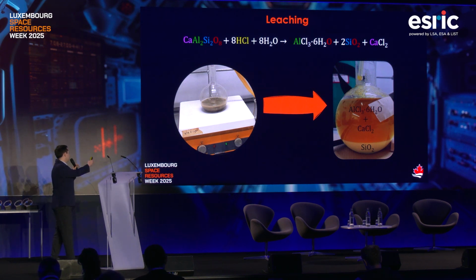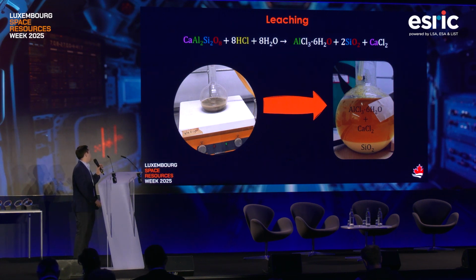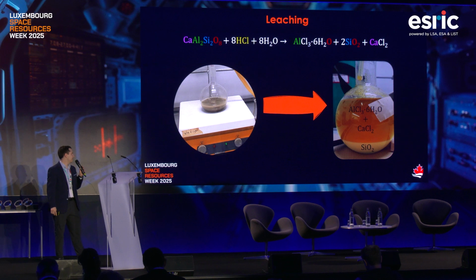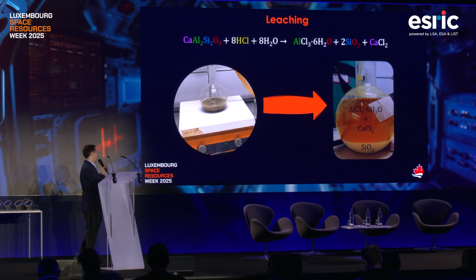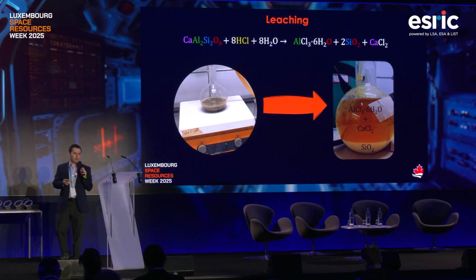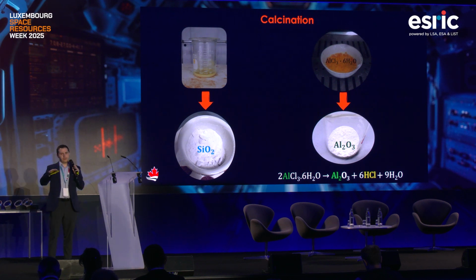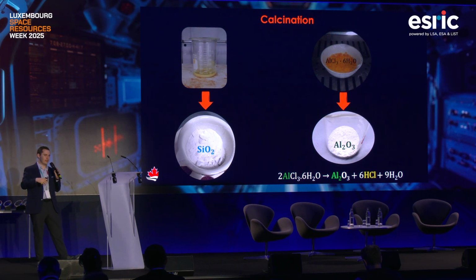So you can see on the first picture, we have our regolith in contact with the HCl solution. And then you can see the products after the leaching. On the bottom, the precipitate, we got silica, mostly precipitated. And then the supernatant is mostly aluminum chloride hexahydrate with a mixture of calcium chloride. Then we separated both phases, the liquid from the solid phase, and then we did a calcination step in order to purify our components, remove any liquids.